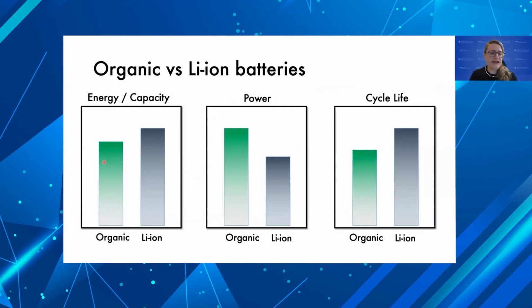In terms of energy and capacity, the organic battery doesn't have values quite as high. I can point to some chemistries that have outstanding capacity for the organic battery, but then they have problems with cycle life or chemical degradation. However, the organic battery chemistry tends to have a much higher power, and this is a result of the mechanism of how energy is stored in the organic battery. The lithium-ion battery relies on intercalation, which can be diffusion limited. The organic battery, as we'll discuss, has an entirely different mechanism of energy storage, and it tends to lend you a high power. So that's an advantage.